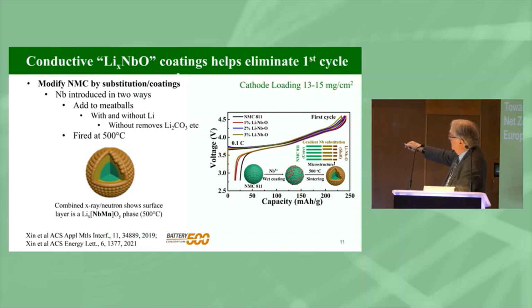So we've now got this mixed phase, and this mixed phase does indeed reduce this first cycle loss by between 40 and 50%. Okay. So it clearly works. We can get some of this effect with aluminum, but it's not as much. And you notice here we only need 1%, whether it's 1, 2, or 3% makes no difference. So just a trace of niobium in the surface will reduce that first cycle loss.